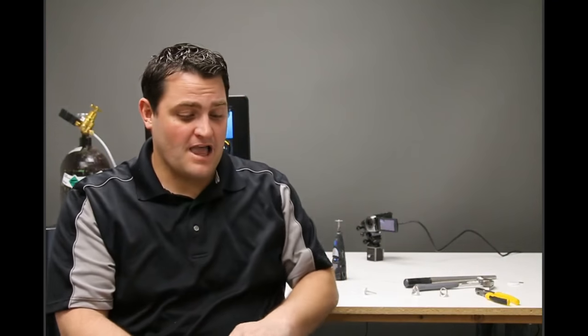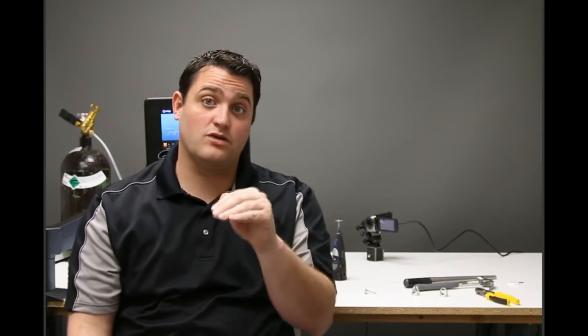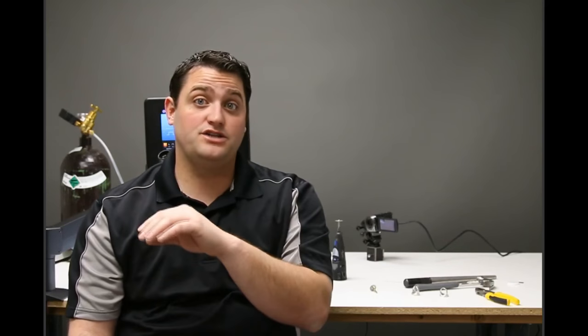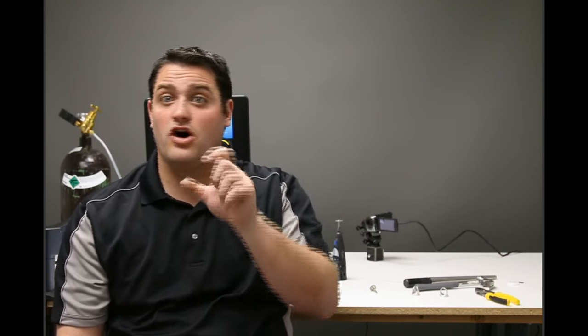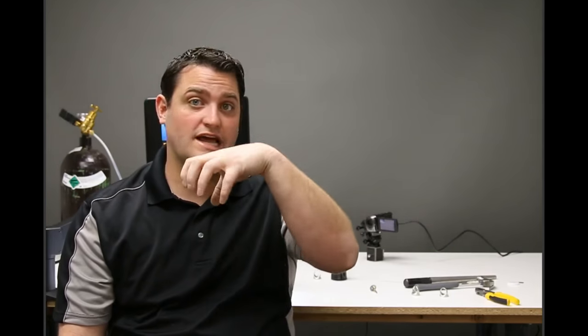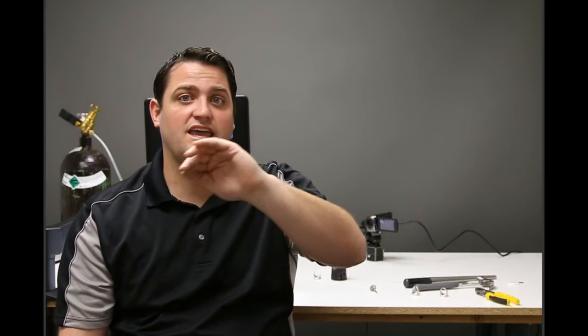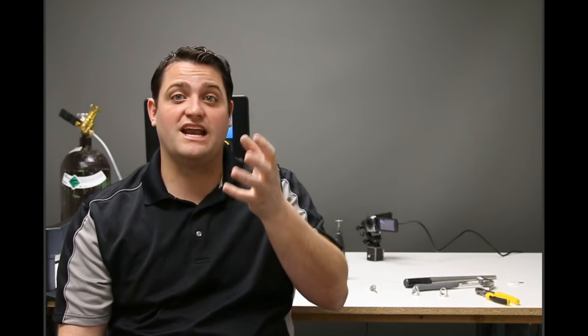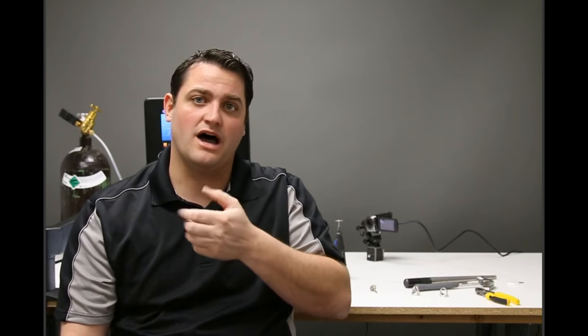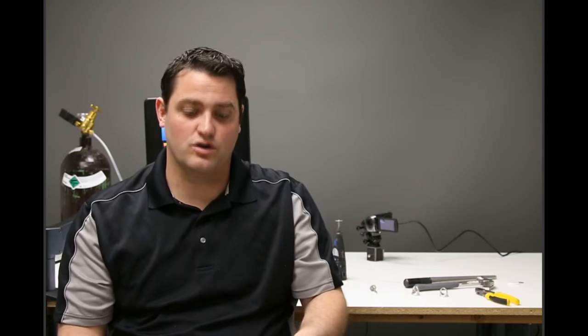Now, if we've got a good hot piece, it may not be as important. But certainly if you're having problems specifically with brittle welds in silver, spreading those welds out and getting a good annealing across that part can alleviate the problem a lot. Again, C mode: some people will finish their welds in the standard weld, and then on the I2 they'll come back in C mode all over the top, and what that's doing is adding a ton of heat and evenly dispersing it so you don't get any cold weld or cold joint spots, but we make sure we get a good hard solid weld.